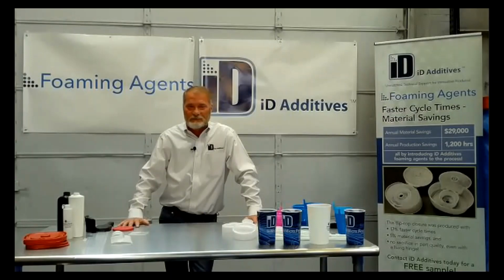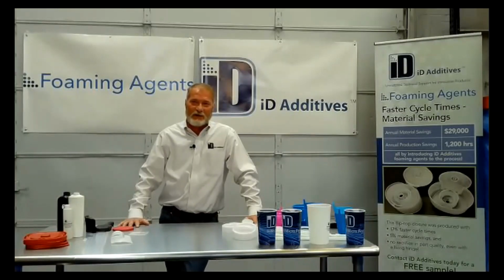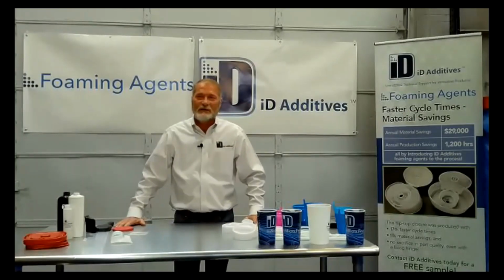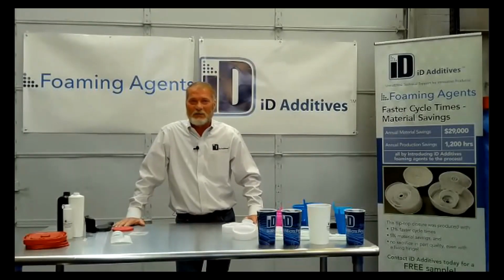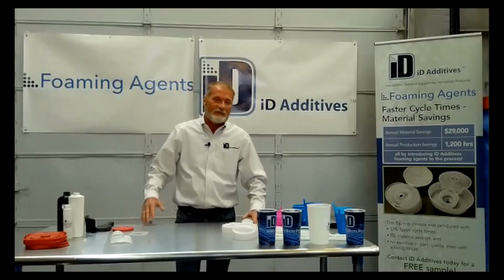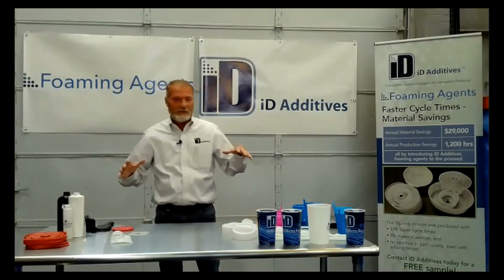Very good. Going back to some of our earlier questions as well, how does foaming agent impact fiber reinforcements? Do they cause issues with directional alignment and compaction? Actually, when it comes to glass fibers and calcium and talc, as far as the alignment of the glass, I've never had any problem with that, but I do know that when you add foaming agent to any filled material, man, does it open the process window up. It does flow much better, and it foams really well with these materials. And I've done glass and talc and calcium, all of them.